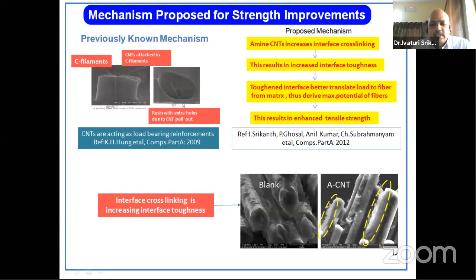So what we propose is that the nanotubes we are using don't have the critical length. They don't act as a load-bearing reinforcement. If you want them to act as a load-bearing reinforcement, you should have a minimum of 200 to 300 microns length. But if you go for that much length, they will get agglomerated too much. You cannot disperse them easily. If you go with the smaller length, they don't act as a load-bearing reinforcement. So we published this in 2012.